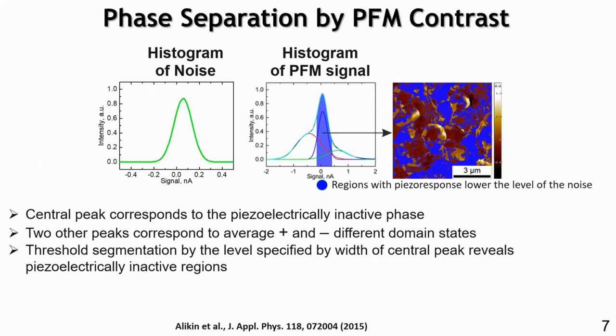So how do we do that? We just do a scan of the surface of the material, and we check the histogram of the piezo response. Usually it looks like the image in the center of the slide. And you see that it's an overlapping of three big peaks. The peak in the center is related to the noise level, so it's related to the absence of piezo response. And the right and left peaks are different domain states, so states with the polarization approximately up and polarization approximately down.